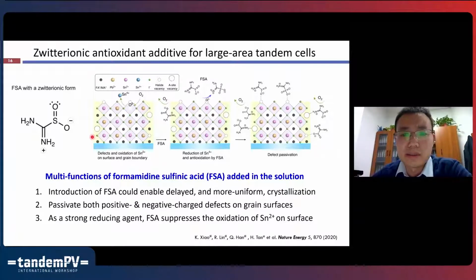a kind of zwitterionic antioxidant molecule. We think there are 3 main functions of this molecule when we make the films. The first is that it has a very strong coordination ability with the tin and lead ions, so we think it might enable a delayed and more uniform crystallization process when we make the film. And also because it is a zwitterionic molecule, it may passivate both positively and negatively charged defects on the grain surfaces. And this molecule has a very strong reductivity, so it may suppress the oxidation of the tin 2+ ions on the perovskite grain surface, and also suppress the oxidation of the tin ions in the precursor solution.